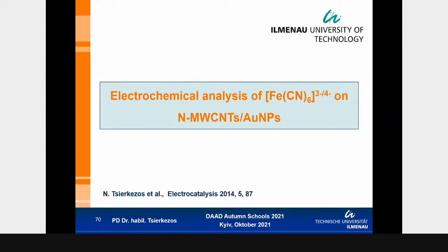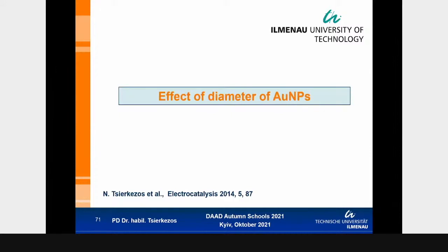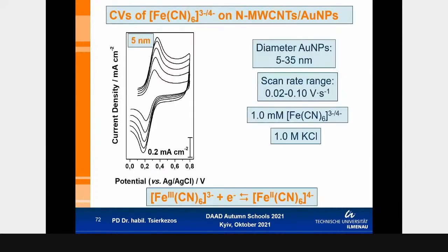The electrochemical analysis of the standard redox system has also been done in the presence of metallic nanoparticles. That means that we modify the nitrogen-doped carbon nanotubes and the other carbon nanotubes with metallic nanoparticles, and we investigate the effect of the modification on the electrochemical behavior of the carbon nanotubes. As an example, I show now the measurements which have been done on gold nanoparticles with various diameters in the range from 5 to 35.